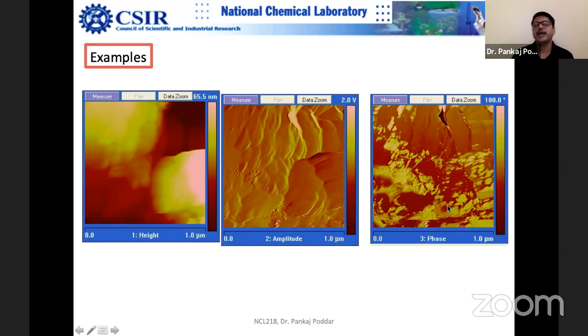You can see this image is quite different, and phase is in degrees. You can see this is a 180 degree scale. So this color means there is no phase change here. It's the same phase, but you can see that somewhere on these patches there is a large change in the phase. This is associated with a change in the slope, which can lead to phase change, and also a change in the property of the material. So this is sensitive to the material properties as well as slope change. And this is very useful actually.